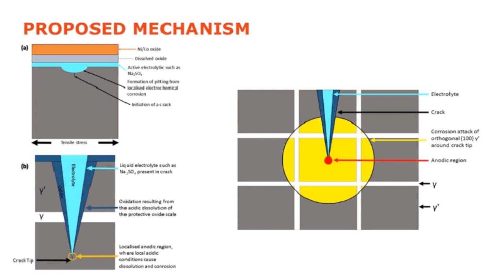So we see our electrolytes wicking down the crack, and we see oxidation happening around the crack tip, and we'll see a localized anodic region somewhere near or at the crack tip, and really that's where we've got sort of acidic conditions and dissolution of the oxide and the substrate going on. And I think it's that localized nature really that drives this mechanism. We don't see broad fronted attacks, we see very localized attacks which cause colonies of cracks.